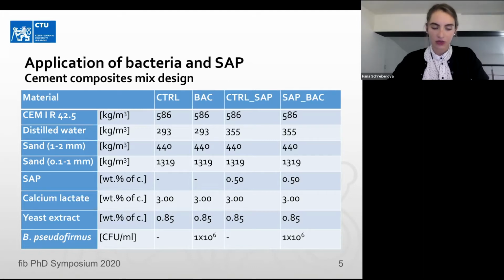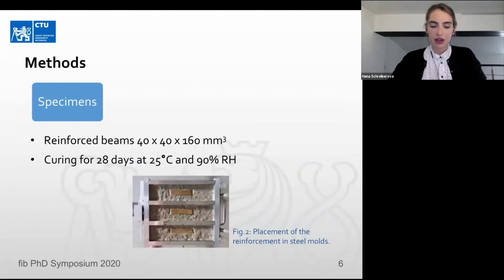In the case of SAP addition, extra mixing water was added to the mix in order to make up for the liquid absorbed by the polymer, so the paste workability remained similar to the control series. Firstly, the prepared pastes were casted into steel molds with reinforcement, as you can see in figure 2. And after 24 hours, the specimens were demolded and cured in the climate chamber for 28 days.